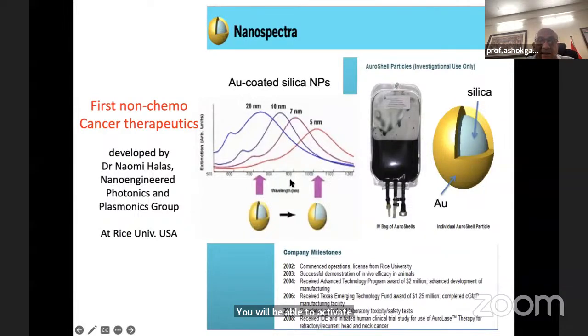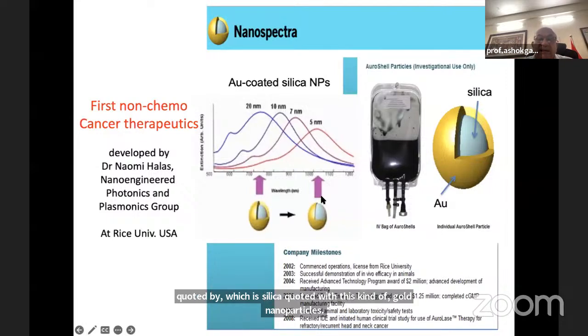different light. So for 5 nanometer gold, you can use near IR radiation, which is around 1050 nanometers. As you know, you don't want to use very high energy radiation. So near IR radiation, around 1050, 1100, is good for biological systems. If you have 5 nanometer particles, silica coated with this kind of gold nanoparticles, they can be excited by this 1100, 1050 radiation.